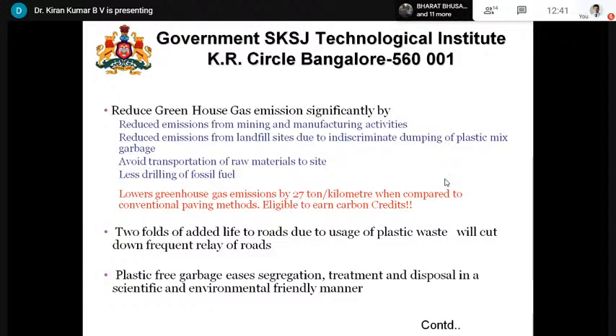Two-fold life is added to these pavements. How? By adding plastic, we are increasing its load carrying capacity. Basically, this plastic tries to cut off the water which is trying to debond the bitumen and the aggregate. So this plastic increases the adhesion property of the bitumen and gives you the complete freedom of this plastic road, even if our drainage fails or chokes, or even in flooding conditions. And the second thing is, we are bringing a plastic-free garbage center which completely composts the green waste and reduces the burden on landfills and other sites.